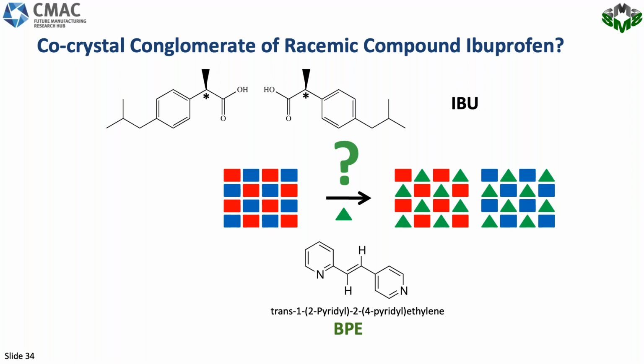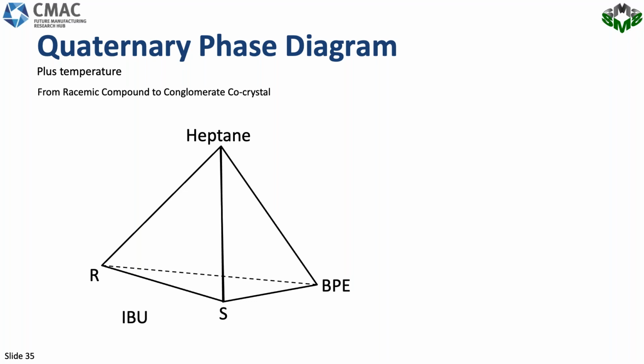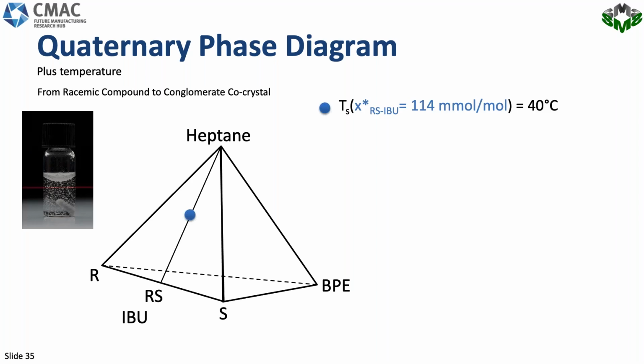But this is a rather difficult system because you have a solvent, the two enantiomers, and then the coformer, BPE. And then we do clear point measurements, so we also vary temperature. So we have a quaternary phase diagram with the additional variable of temperature. But still, if you do it schematically, you can do very nice measurements. We crystallize from heptane, and we can start with a racemic solution and determine the clear point of a composition with a certain concentration. We chose the composition of 114 millimoles per mole of Ibuprofen, and the clear point, the point where a suspension turns into a clear solution upon increasing the temperature, is 40 degrees.